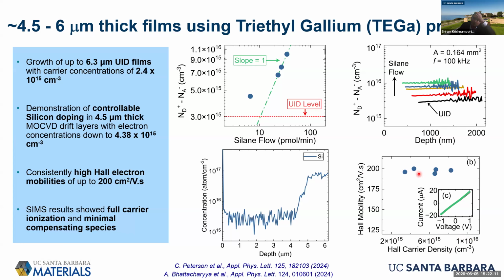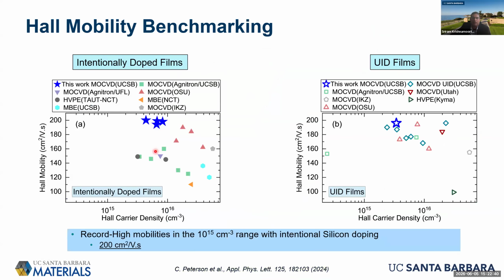The reason this is flat is that gallium oxide is a low symmetry crystal. There are lots of phonon modes. There's a strong electron-phonon coupling and Fröhlich interaction. So the theoretically expected mobility at the low doping regime is indeed close to 200. So we've been able to get films that are close to theoretically predicted values in terms of electron mobility. So we do have these high quality films in gallium oxide. Generally in the literature, when we get to lower electron density values below 10 to the 16, you start to see a drop off in the mobility because of compensation effects. But by carefully tuning the growth conditions, we've been able to cross that barrier and get a much higher electron mobility in these films with intentional doping.